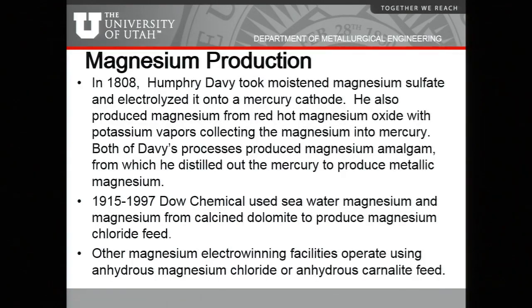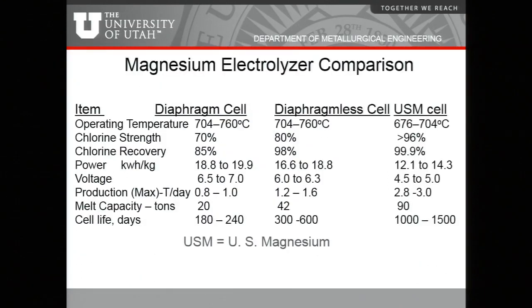Most of the electrowinning is done with the magnesium chloride systems, and they use anhydrous magnesium chloride, which is actually a little bit tricky to make and to not have interfering magnesium oxide that reduces the current efficiency and the conductivity of the electrolyte. It causes problems in terms of sludge and other things. And that's actually something that's been, I think, a nice innovation that's allowed for some improvements in some of the technology there with magnesium. This is just some general information that is out there for some of the older cells and some more modern cells.